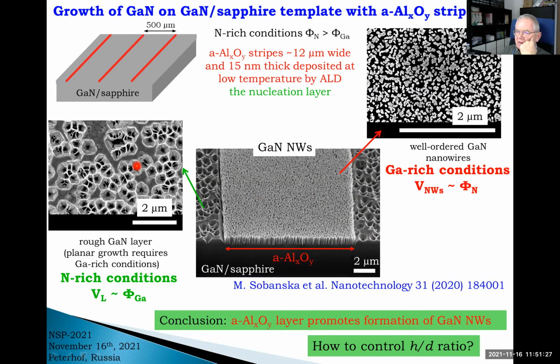Here you have the result. On this gallium nitride part, we have low quality gallium nitride because we are growing at not very high temperature and in nitrogen rich conditions, while planar growth requires gallium rich conditions. So the quality of the GaN is pretty low. But here we have very nice nanowires. So again, this example shows that the aluminum oxide layer promotes formation of nanowires. Now, we want, of course, to control this growth in such a way as to get as much gallium as possible incorporated into nanowires while keeping this parasitic film as thin as possible.